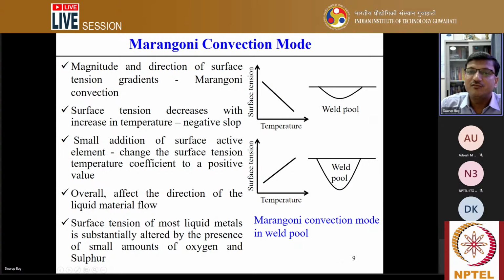That usually creates a weld pool with a different aspect ratio. In that case, the depth of penetration is low and the width is much more, and it actually decides the flow pattern, and from the center to the outward periphery there is a flow of the molten metal. The other way, a very small addition of the surface active elements changes the surface tension gradient, and in that case the surface tension gradient can be positive. Once it is done, the shape of the weld pool will change accordingly. The material flow pattern is from the outward periphery towards the center. In that case, it increases the weld depth and decreases the weld width.